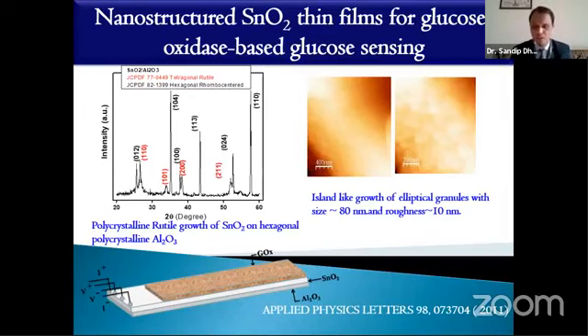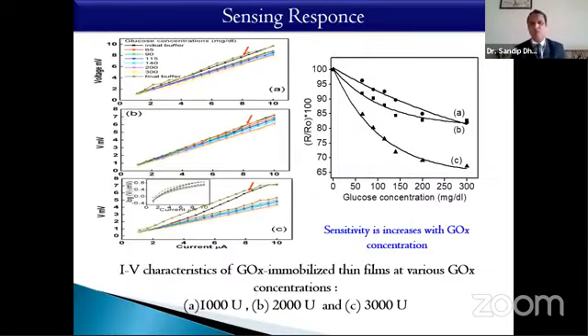So here we have the properties, or I can say characterizations, like X-ray, which confirms this structure is SnO2 on alumina, and this is a surface morphology, these are AFM or atomic force micrographs of our tin oxide, which have elliptical granules of size 80 nanometer and roughness of 10 nanometer. So if roughness is more, adsorption will be more on the surface and it will sense the glucose entity. So here we have a result, and this work was published a few years ago in Applied Physics Letters.